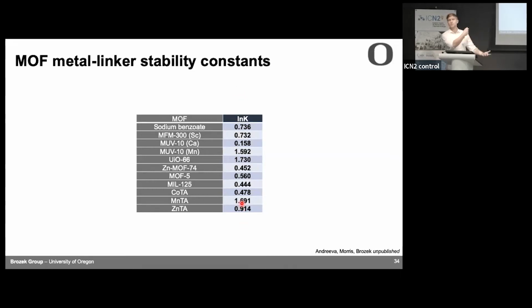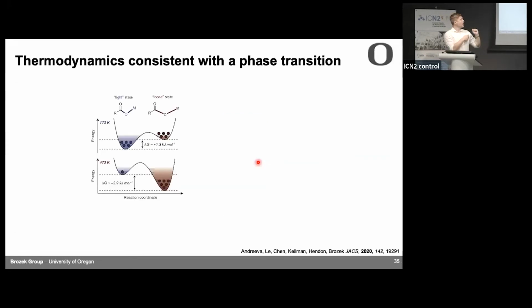So this is useful. When people are trying to design some new chemistry for, I don't know, let's say MIL-125 or MUV-10, if you're in Valencia and you're studying MUV-10, you can think about how dynamic those bonds are. The other thing is, this is consistent with the idea that UiO-66 is the most stable MOF because it has the largest equilibrium constant. But it's still not a very big number, which means that even in UiO-66, those bonds are probably pretty dynamic. Okay, well, with the data, we figured we should also be able to understand the energetics of this process. You should be able to fit the data to a Van't Hoff relationship.